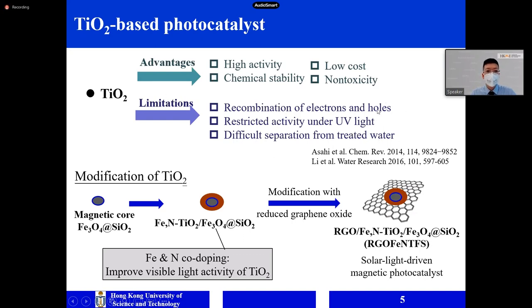To tackle these problems and to apply this technology in the real world, we further modified the photocatalyst. First, we make a magnetic core, iron oxide and silicon dioxide, and then put the modified titanium dioxide on this iron core as the shell. The method we improve this titanium dioxide is using iron and nitrogen co-doping. By using this way, we can improve the visible light activity of titanium dioxide. Furthermore, to improve the performance of the material, we use reduced graphene oxide, the short form is RGO, on the outer layer of the whole material composite.